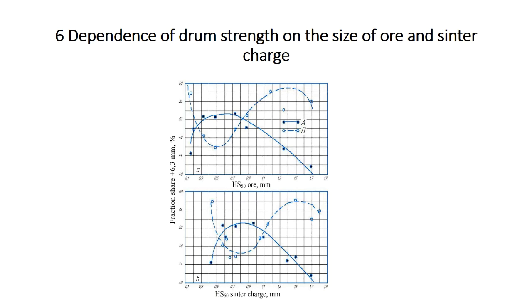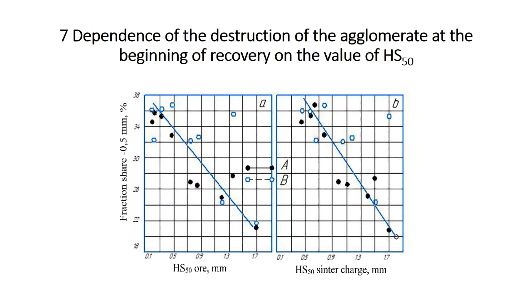Figure 7 shows the dependence of agglomerate abrasion on the size of the ore and sinter charge. At the same time, a decrease in abrasion is seen with an increase in the size of the ore batch. No differences were found between magnetite and hematite ores. The points for both ore grades are evenly spaced around the straight line. When determining the dependence of abrasion on the content of the fraction minus 0.5 mm, it was found that when the content of this fraction is more than 10 Wt%, the abrasion remains constant even at very unfavorable values of 32 Wt%, and decreases only when the content of the fraction minus 0.5 mm is below 10 Wt%.